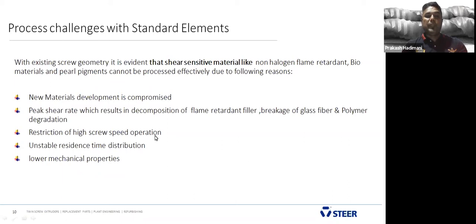There is a restriction of higher screw speed, because the extruder is built for 1200 rpm, but we have to restrict ourselves. When you are going at 1200 rpm, because of the peak shear, the polymer starts degrading and turns yellow. That's why many operators compromise themselves to run at a lower RPM, 600 RPM. Okay, how to overcome this situation? Residence time is also not stable. Every time there is a change in the residence time, and it also lowers the mechanical property. When the polymer starts degrading, the mechanical property drops down.